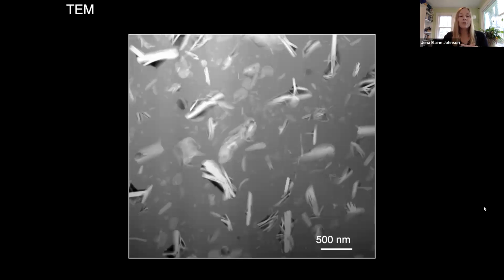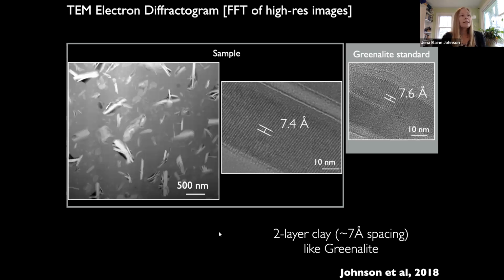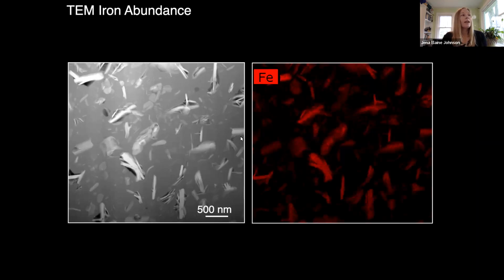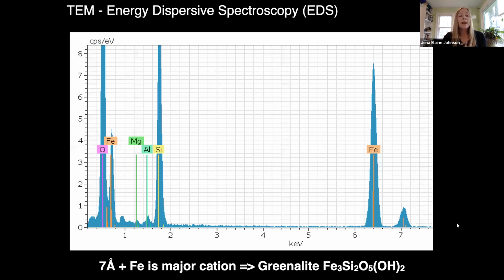So the clearest method was transmission electron microscopy, or TEM imaging. So here we could see the individual particles that were really a variety of sizes, but mostly 500 nanometers or less. And as this example shows, this TEM high resolution imaging identified these particles as having approximately 7 angstrom spacing, which is consistent with greenalite. And as we mapped iron, we saw that iron was really only in these particles. And in fact, using energy dispersive spectroscopy, we could see that the major cation in these particles appears to be iron, confirming that these mineral inclusions are greenalite.